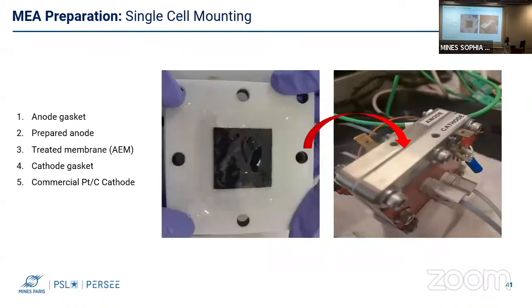After that, the cell is assembled by mounting the different components on top of each other, starting with the anode gasket, the prepared anode, the treated membrane, the cathode gasket, and the commercially available platinum on carbon cathode. The polar plates are then screwed together in order to obtain a cell ready for testing.